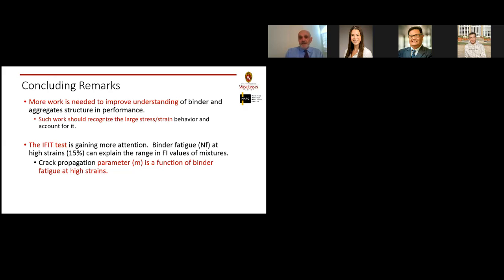So I'm very happy actually after all of these years of development of the IFIT, we can bridge the gap between these different scales. You know, for good reasons, you started with the mixture testing, but we wanted to convince ourselves that this behavior can relate to probably a little bit smaller scale, which is the binder scale. We also did a lot of mastic testing, and we can confirm that at the mastic scale, we can support your analysis procedure for the IFIT.